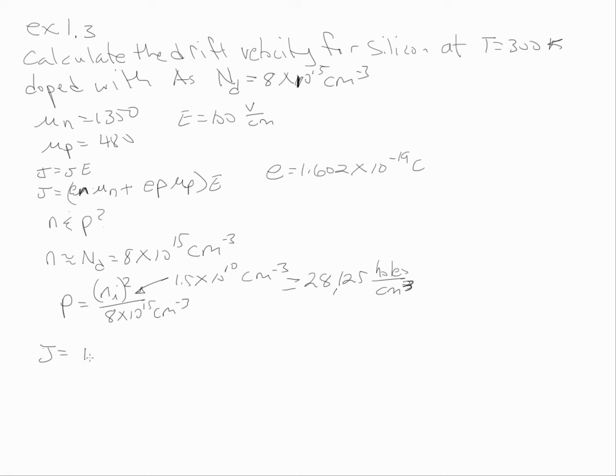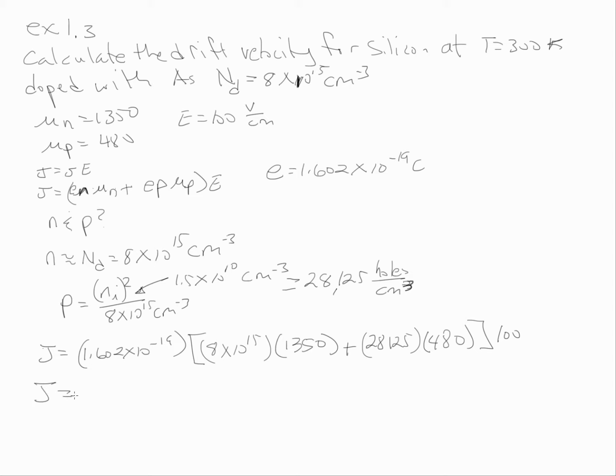We just plug in the fundamental charge, and then we put in the concentration of electrons, 8 times 10 to the 15th, times the electron mobility, which is 1350, and then we put in the concentration of holes, which we just calculated, times its mobility, which is 480, and then all times the applied electric field, which was 100 volts per centimeter. And you come out with J equal to 173 amps per square centimeter. So pretty high amps per square centimeter.